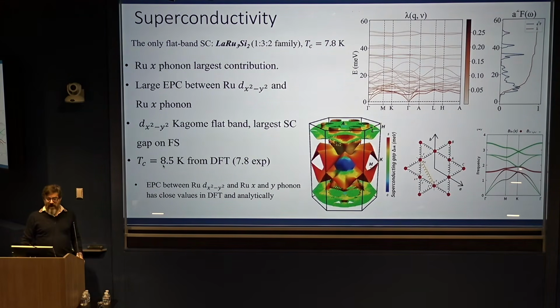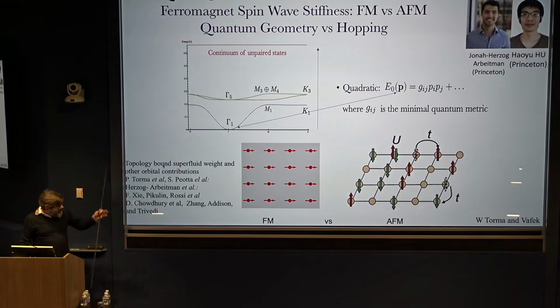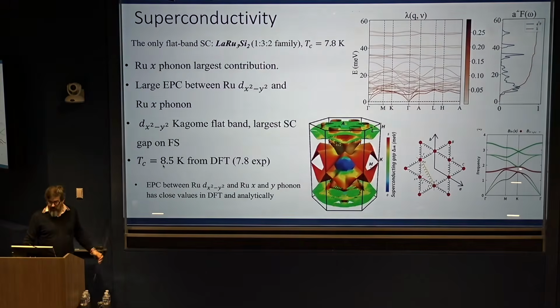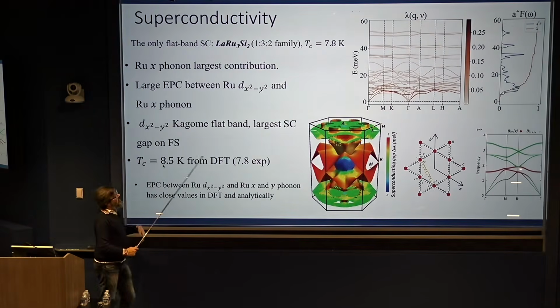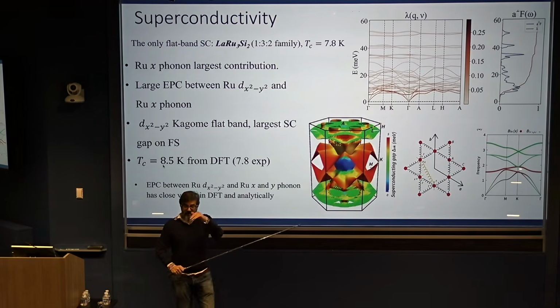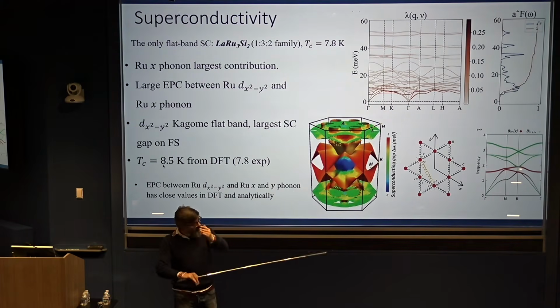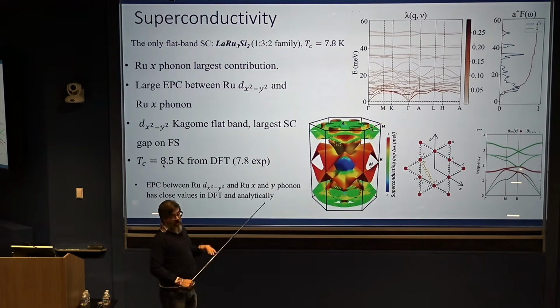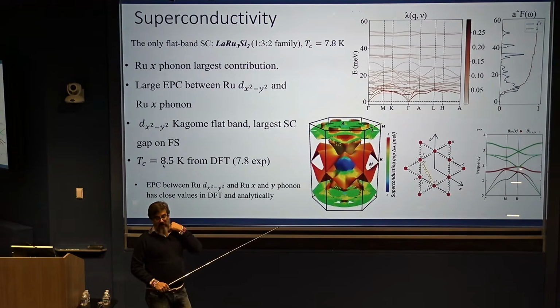So if you have a system that's actually fractionally filled at filling half or whatever, it'll either magnetize, ferromagnetize if you've got large quantum geometry, or anti-ferromagnetic if you don't have large quantum geometry, but it won't likely superconduct. So that's the reason why a lot of these Kagomes, flat bands, are not at the Fermi level, they ferromagnetize. There are some Kagomes where flat bands are at the Fermi level and superconduct.